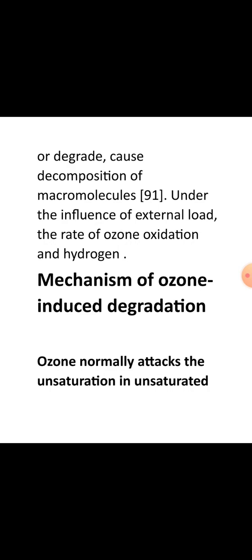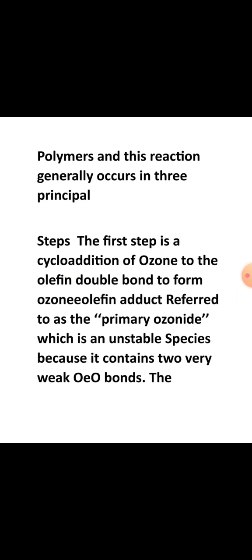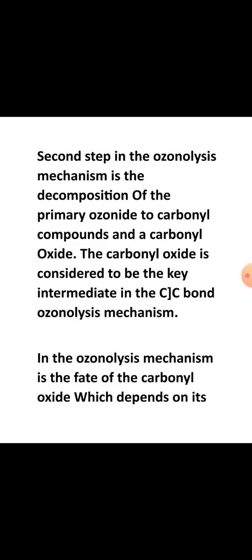Mechanism of ozone-induced degradation. Ozone normally attacks the unsaturation in unsaturated polymer, and this reaction generally occurs in three principal steps. The first step is a cycloaddition of ozone to the olefin double bond to form an ozone-olefin adduct referred to as the primary ozonide, which is an unstable species because it contains two very weak oxygen-oxygen bonds. The second step in the ozonolysis mechanism is the decomposition of the primary ozonide to a carbonyl compound and a carbonyl oxide. The carbonyl oxide is considered to be the key intermediate in the carbon-carbon double bond ozonolysis mechanism.